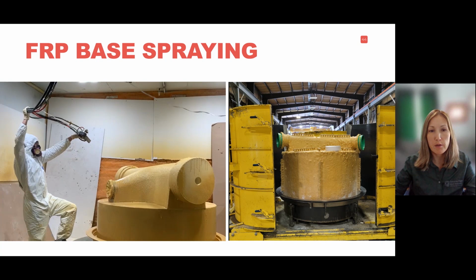So, another image showing how we manufacture those liners. Basically we spray the negative mold with the FRP. Once that mold is completed, we place it in a form, then we close it off and pour concrete over. Then we flip it and your base is ready. With these manholes, we can do technically any configuration. We have a robot that cuts the channels or the negative form to any configuration. If you have 3-way, 2-way, 8-inch, 10-inch, we can make it all to whatever your imagination is.